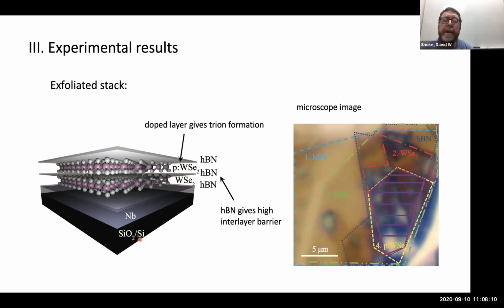It makes a huge difference, by the way, that we have hBN encapsulating everything. If you look at this picture here, it's metal, hBN, monolayer, hBN, monolayer, hBN. This is why I said it was a real project, seven layers high for the lab members. You certainly don't want the metal pushed right up next to the monolayer. That will do bad things, right? So the hBN between the metal and the first monolayer is an important part of this. You don't want current flowing in the vertical direction.